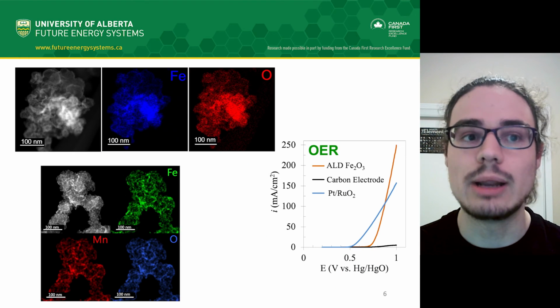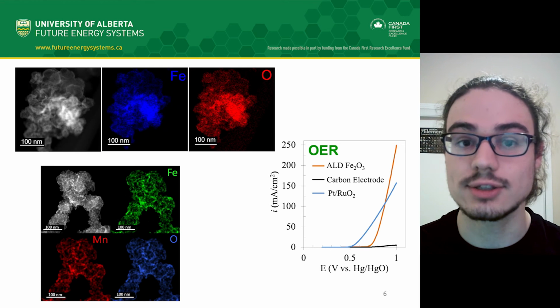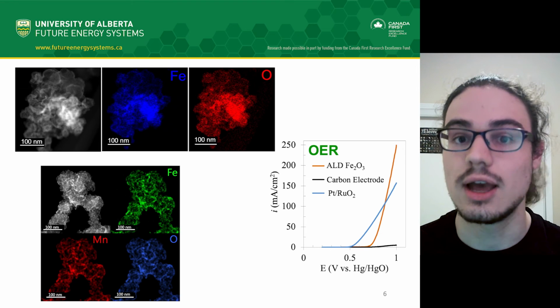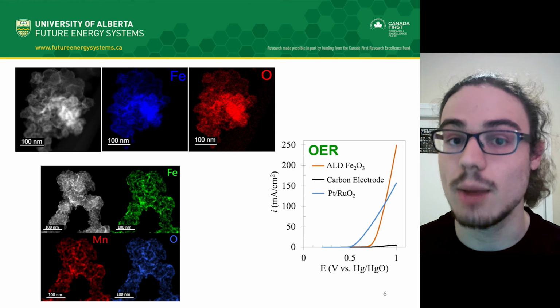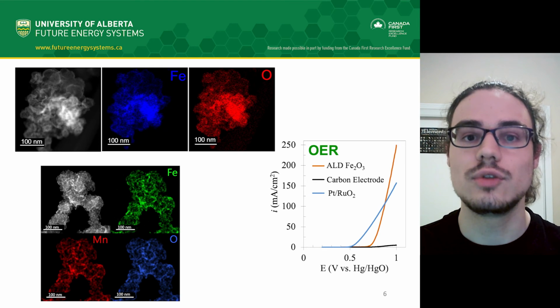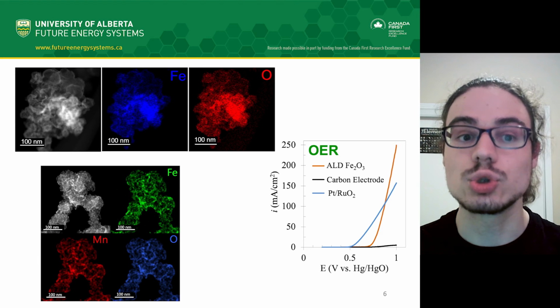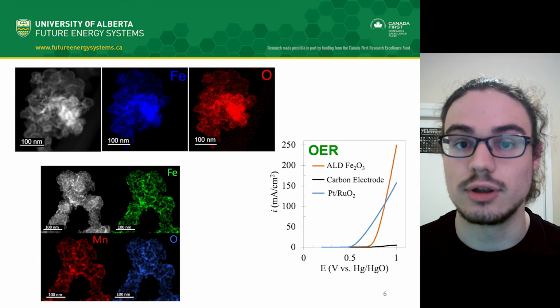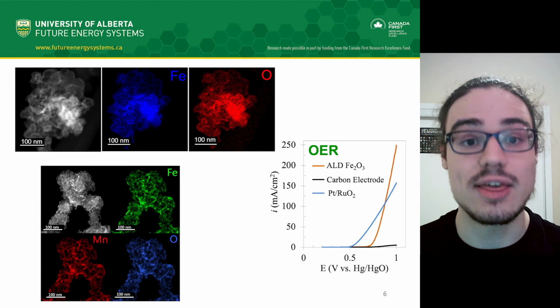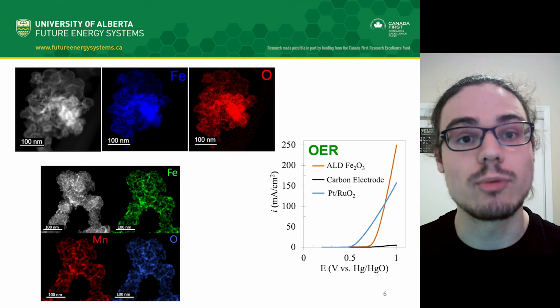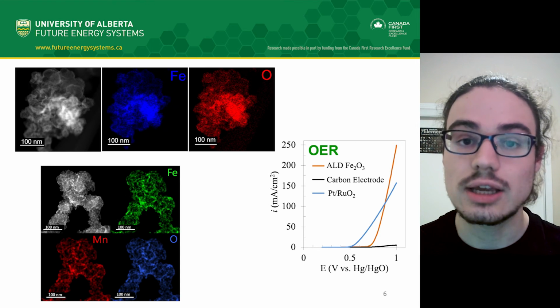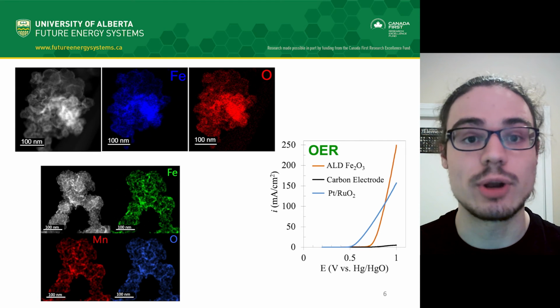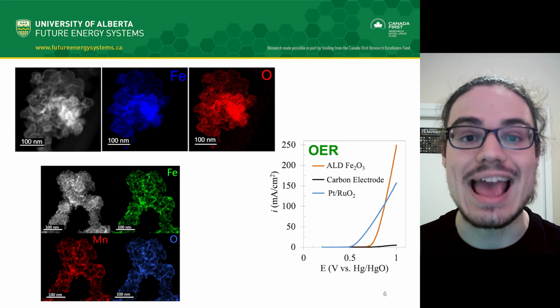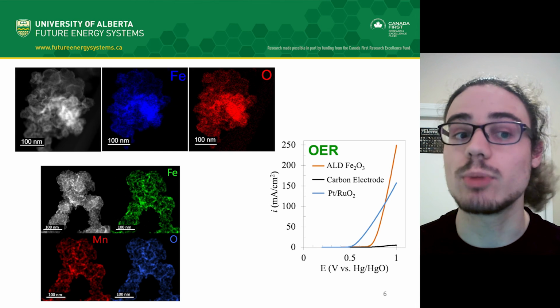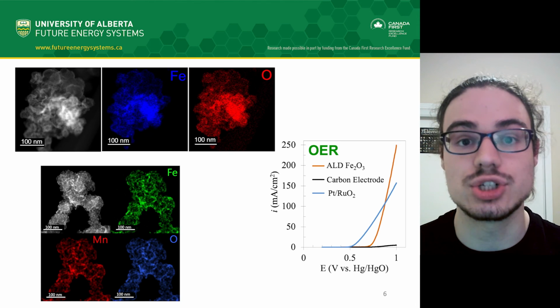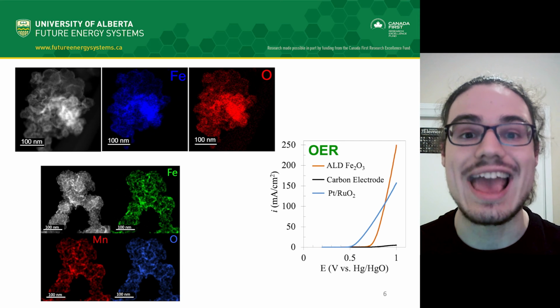In my work, I've been able to show through electron microscopy and X-ray microanalysis that I can in fact create a 10 nanometer thick iron oxide catalyst on the particles of carbon that make up the electrode. The electrochemical results of the iron oxide catalyst show a lot of promise towards the charging reaction of a Zinc-Air battery. However, 10 nanometers is very thin, and thicker catalyst layers could improve the performance even more. Currently, I'm working on combining two or more transition metal oxides, say manganese and iron oxide. This could open the possibility of thicker films and the ability to catalyze both the charge and discharge reactions in a Zinc-Air battery.